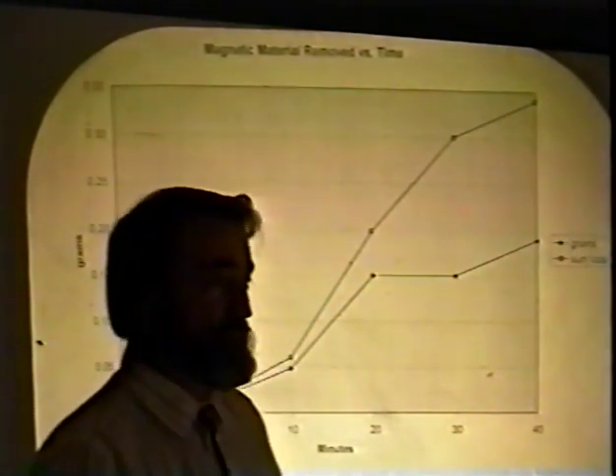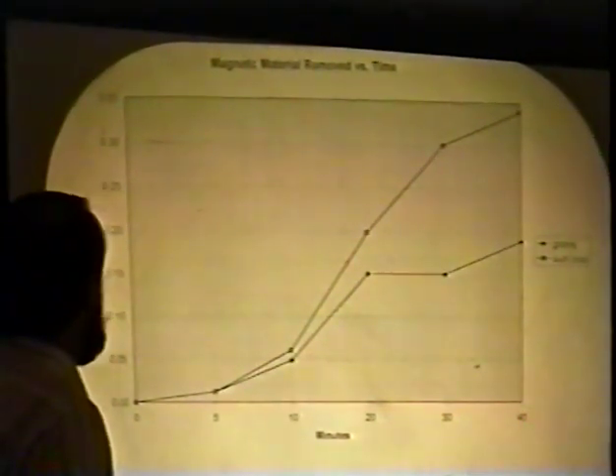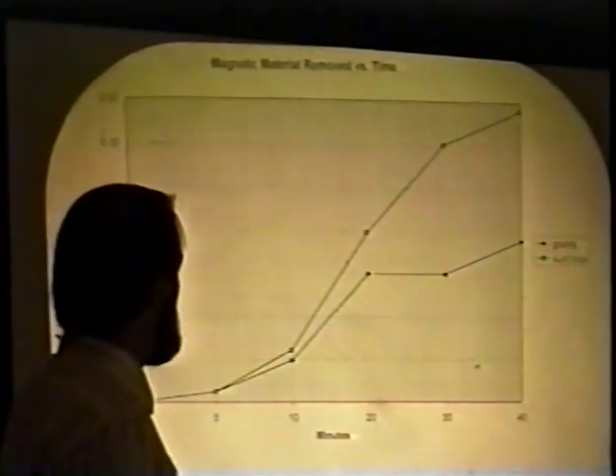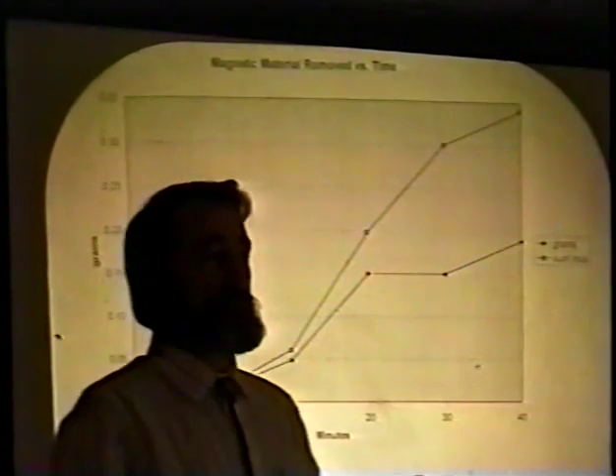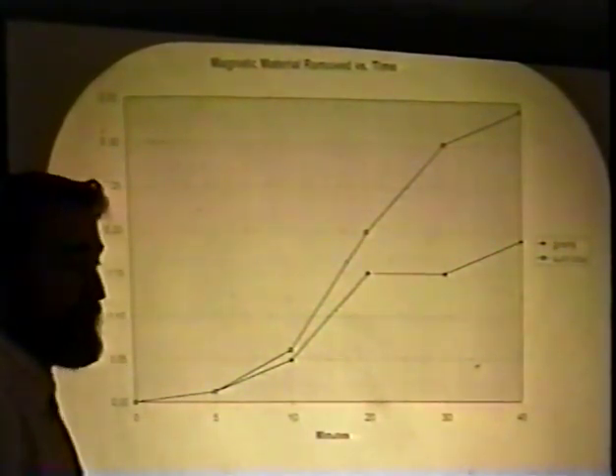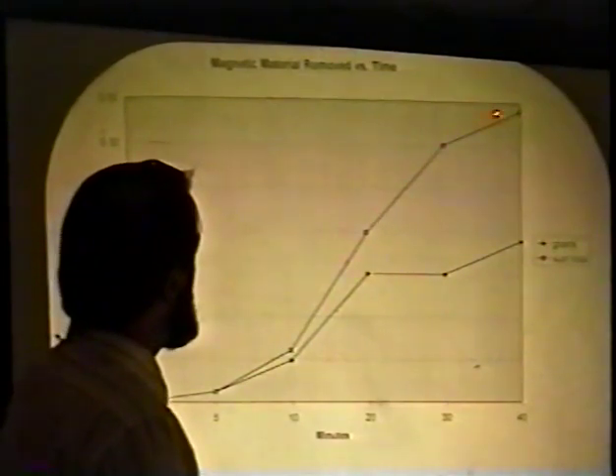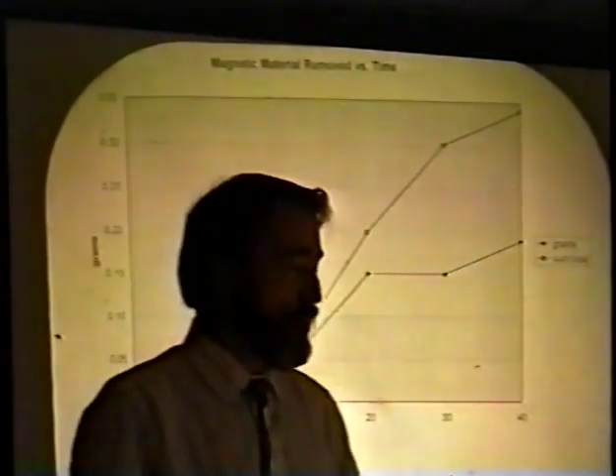Now this is an interesting graph I found when I looked at Dr. Bachrach's and Sundaresan's paper on the amount of material that they removed. This is a plot of magnetic material removed versus time in minutes, from 0 to 40 minutes, and grams of material from 0 to 0.35 grams. The lower chart shows how much material is pulled out after each 10 minutes of processing: process for 10 minutes, let it cool for 5 minutes, process for 10 minutes, let it cool for 5 minutes, and each time you pull out a certain amount of material. It turns out there seems to be a diminishing point of no return in this curve, which shows the sum total of the material pulled out. This curve tends to go up and level out to a point where you're not going to get any more material out of the pile of carbon, no matter how much you stir it and spark it.